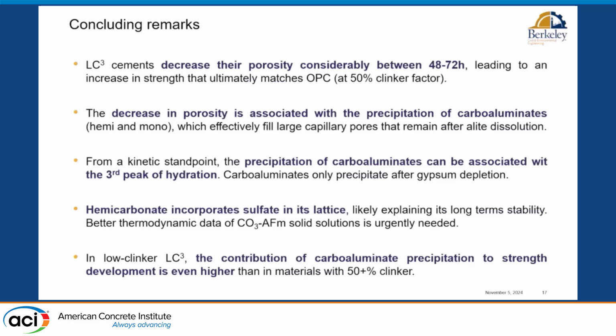From a kinetic standpoint, this precipitation can be associated with this third peak of hydration, which I think is really nice, because if we just want to study when this precipitation is happening, we don't really need to do XRD. You can just look at the calorimetry curve, and wherever this third peak of hydration is will tell you when you have your enhancement of carboaluminate precipitation. From a thermodynamic point of view, I think it's interesting that we observe incorporation of sulfate in the lattice of hemicarbonate. And that's a pathway for further work, because certainly we need to update the solid solution models for that phase in our databases.